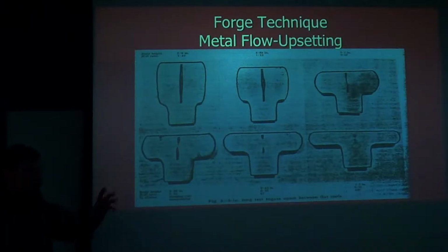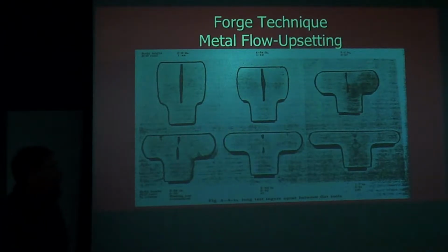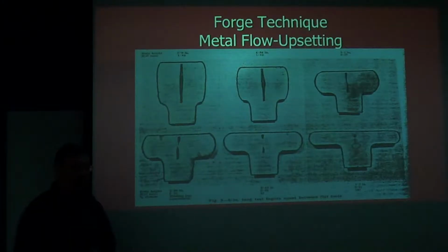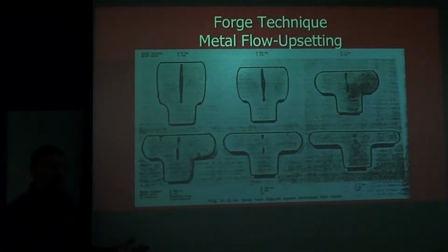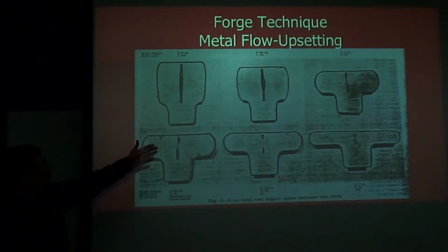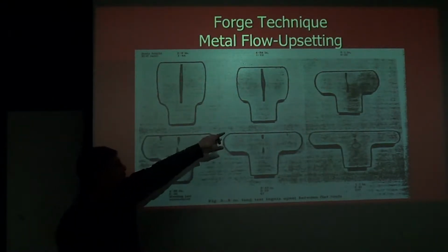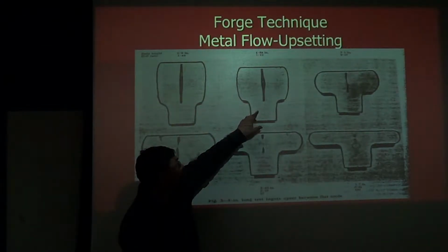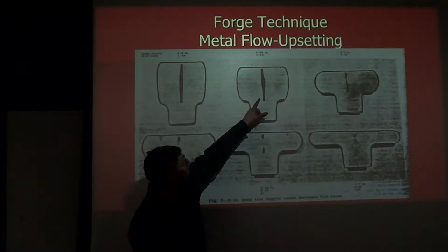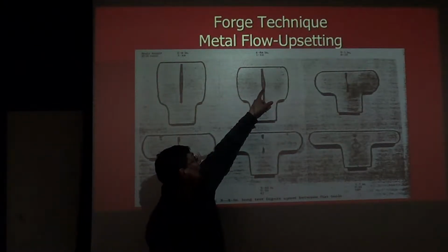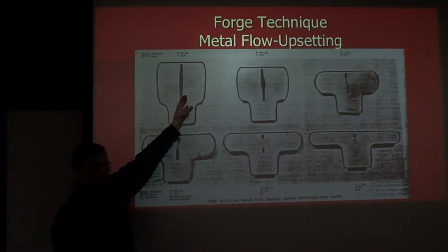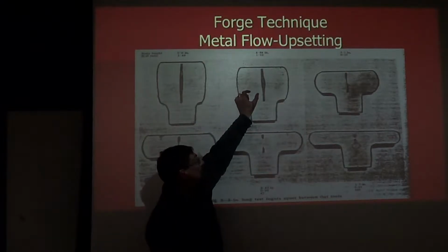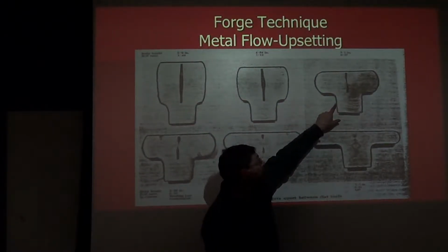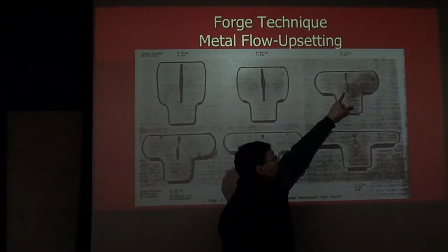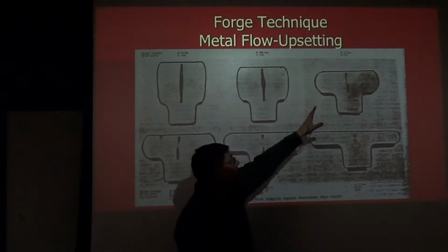So there was some research work that was done quite a while ago where they actually did an experiment where they took slugs of metal and they drilled holes in the center, capped the holes, and then did different amounts of upsetting, and then split that metal back open so they could see what would happen. And you can see here what they did. Initially, right here, this would be sort of the spot that I illustrated that's near the start. If you look carefully, that hole is actually larger in diameter at this point than it was at this point. The hole is getting shorter, but it's getting larger in diameter. Now we're starting to get in this position that the hole is starting to collapse, but it hasn't actually completely eliminated any of it yet.